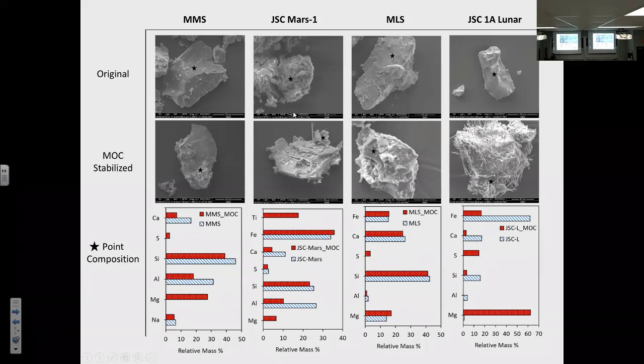The first thing we notice is if you look at just the shape, the morphology of these particles, the original sample looks like what you'd expect of a basalt. A basalt is basically a rock that's been crushed, and there's a lot of glass in it. So there's a lot of sharp edges. It looks like basically shards of glass. And when we put it with magnesium oxysulfate cement, we saw that our shapes are now more indistinct. So there has definitely been some form of either erosion that happened because of the cement, or there's probably been more accumulation of these oxysulfate cement particles on the surfaces of our simulant particles.